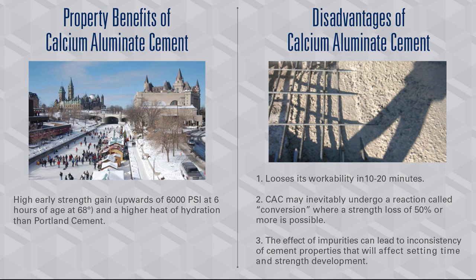The disadvantages of it: it does lose its workability within 10 to 20 minutes. So for self-leveling, sometimes we need a little bit more working time. And it can also go through a process called conversion, which will actually make a gel instead of a crystalline structure, which gives you loss of strength in this material. We can decrease water, add a little extra limestone, which helps eliminate some of that conversion process. And some of the impurities in that will actually affect the strength and setting time development. So having good quality materials is very key to having a good calcium aluminate type cement.